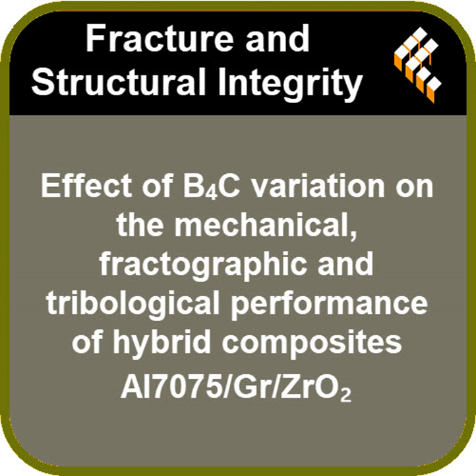And importantly, they made this material using the two-step stir casting method. Which is very economical, right? That's key. Crucial. Stir casting is one of the cheapest ways to mass produce these composites commercially. So after all the testing, where did they land? What was the optimal sweet spot for these reinforcements? It was pretty clear. The best overall performance, both in strength and wear resistance, was consistently found at the maximum B4C content they tested. And that was? 4 weight percent.